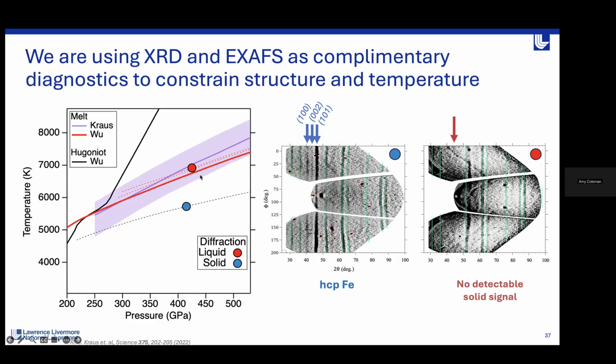As we push up to higher temperatures, we lose sight of those peaks - those solid diffraction peaks go away. Now typically when you think of liquid diffraction, you think of this nice diffuse scattering signal. We don't see that here.